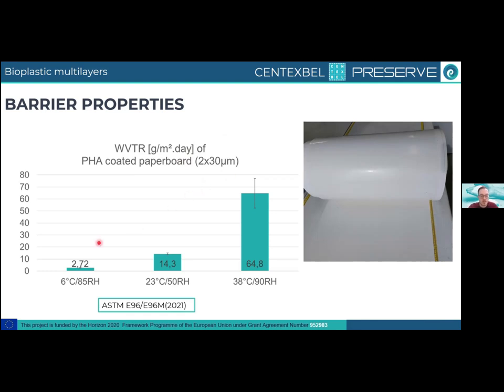You can see it with different conditions. So from 38 degrees with a relative humidity of 90%, or 23 degrees, or even 6 degrees, you can see that we have very low water vapor transmission, very good barrier properties actually, that we can reach with the PHA. You can see as well here the norm that is used for measuring these barrier properties.